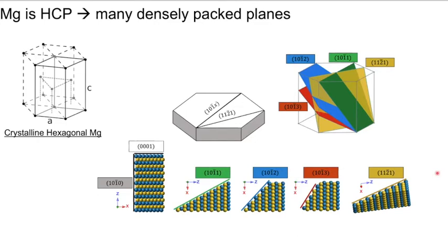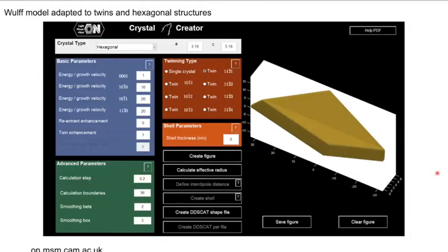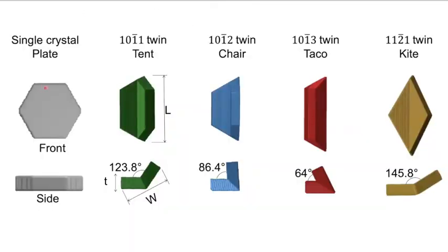And we noticed initially that the structure made these single crystal nanoplates. And in the first paper we published, we said, oh yeah, they all make hexagonal nanoplates. Well, it turns out when we looked more closely, only about half of the particles were nanoplates. And the other things we had were folded plates that were folded along one of the twin boundaries that I just showed. And that fold angle, of course, is dependent on the crystallographic orientation of that boundary.